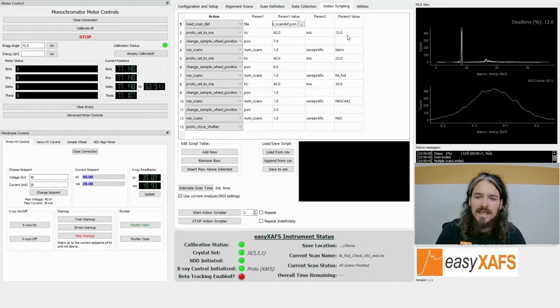First we'll do an I0 scan. That's where we measure through a sample position that doesn't have a sample, so we can see what the raw amount of X-rays are coming from the monochromator without any sample. We'll do that with an X-ray power of 40 kilovolts and 15 milliamps. Then we'll increase the power to 40 kilovolts and 20 milliamps, change the sample position to measure the nickel foil and do a single scan. Then we'll switch to full power, 40 kilovolts, 30 milliamps, and do one scan on the NMC 442 material, and then another scan on the nickel oxide pellet.